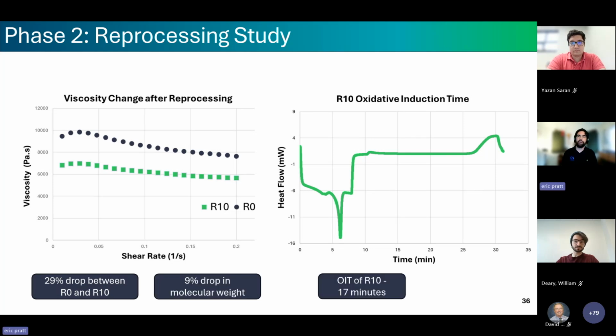The oxidative induction time is our proxy for long-term environmental stability. And even at R10, our 10th recycling process, the oxidative induction time came in at 17 minutes. And while this is a 54% drop from the original material, it's still comfortably within an acceptable range for this application. For some context, the standard oxidative induction time requirement for cable jacketing material is 20 minutes. So nearly reaching the standard for the material itself for our packaging material seemed perfectly fine to us.